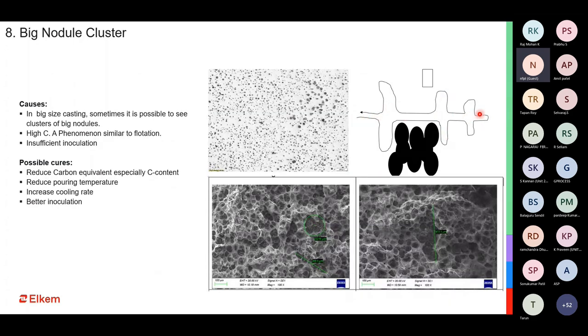We have seen this. This is the dendrite, and then towards the sides of the dendrite, you have graphite being precipitated out. When you have excessive graphite inside the dendrite, and this mostly happens in the hot zones or the heavy sections of the casting, which are last to solidify, when you have too much graphite precipitating in one or two locations within the casting, the nodules try to agglomerate, to combine with each other to get a much better thermal stability, and thereby keep getting bigger in size. And when they keep getting bigger, they appear to be something like this.